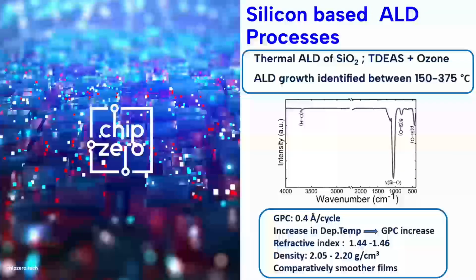Using the TDEAS, we optimized thermal silicon dioxide ALD using ozone as the co-reactant. We were able to deposit these films between deposition temperatures of 150 and 375. And we were able to get quite pure silicon dioxide. Why do I say quite pure? There are also some hydroxyl groups. The growth rate is about 0.4 Angstrom. We observed that the growth rate increases with the deposition temperature. At the lowest temperature, 150, we got a growth rate of around 0.09 Angstrom. And all the properties matched well with silicon dioxide. The refractive index was around 1.46, and these films are comparatively smooth.